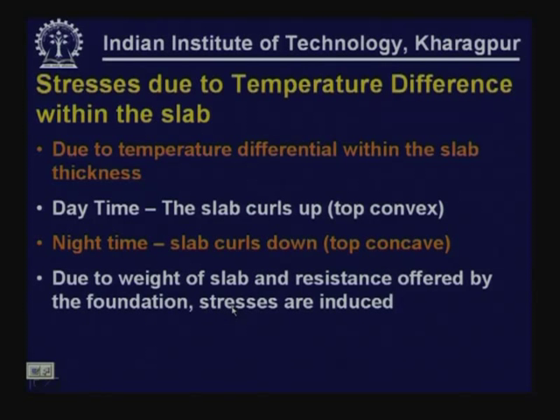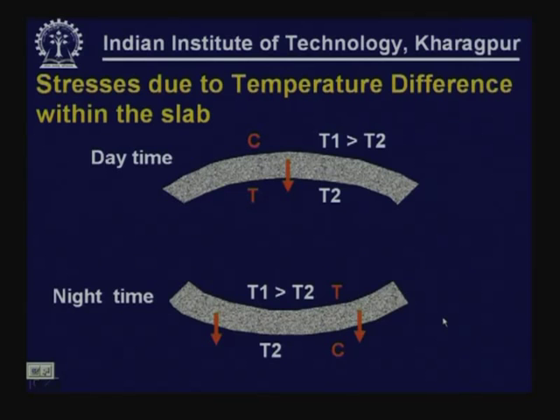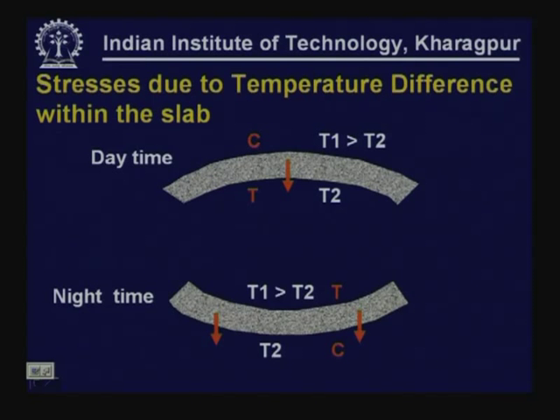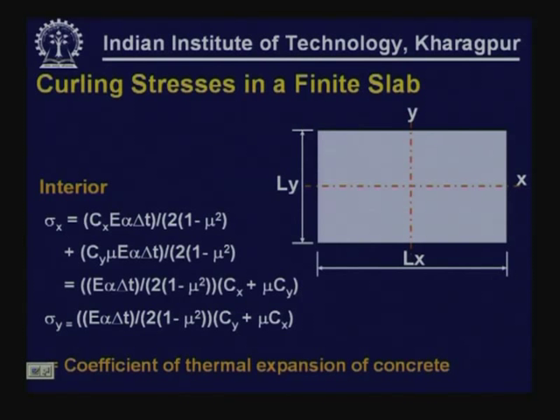There are also going to be stresses within the slab due to temperature difference. Due to temperature differential within the slab: during daytime the slab tries to curl up — top will be convex; during nighttime the slab curls down — top will be concave. Due to the weight of the slab and the resistance offered by the foundation, stresses are induced. The slab will not be fully permitted to curl up or curl down — there is restraint provided by the self-weight and also by the foundation. During daytime, the self-weight pulls it down so there will be tension at the bottom and compression at the top.